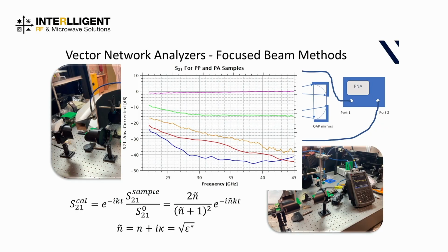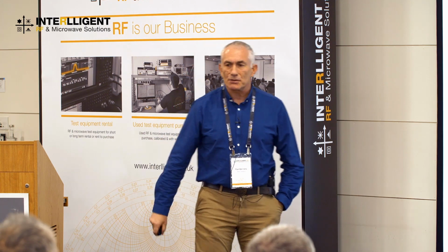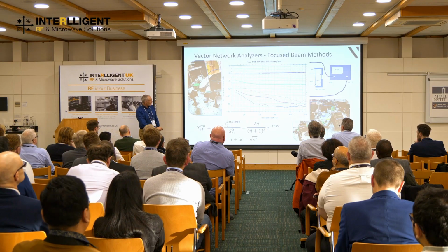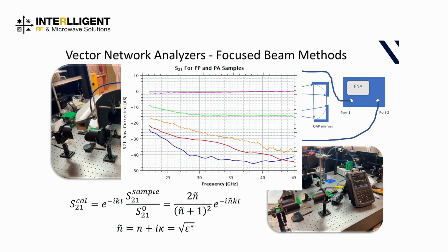So that would be the free line, that black line up there. And as they added inside these particular plastics, we're talking PP, PA, polyamides, as they added inside there carbon nanotubes, you can see that the absorption becomes greater and greater and greater until eventually you get to a concentration of nanotubes where this material can work as a very effective EMF shielding.